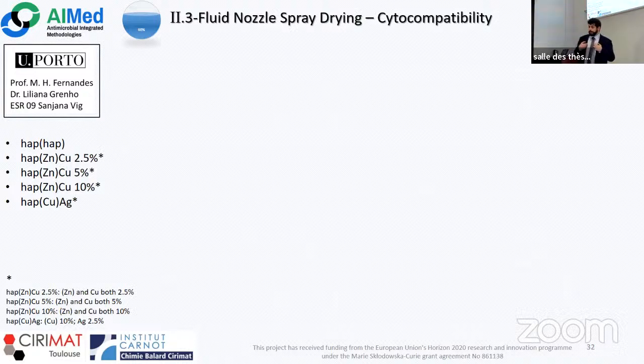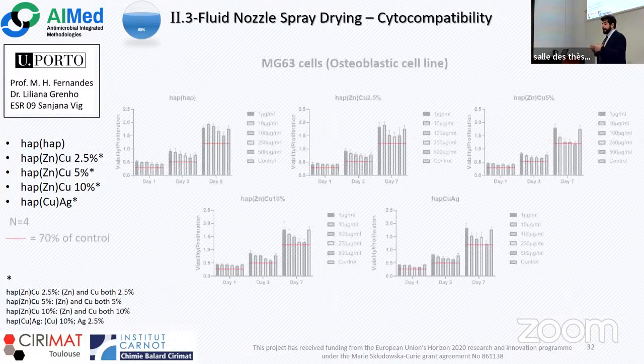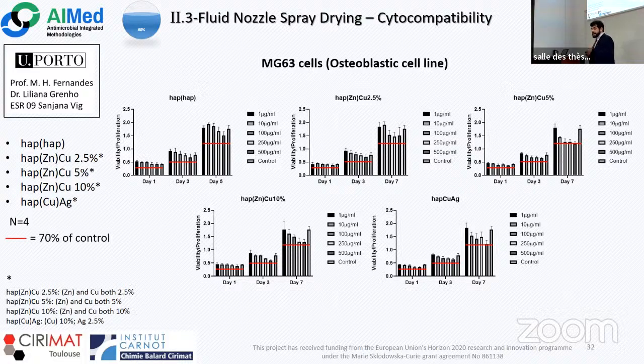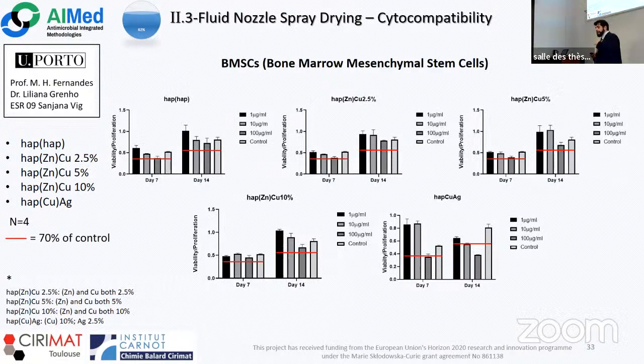And during my stay at the University of Porto, we studied the cytocompatibility against the MG63 osteoblastic cell. We can observe that generally, in all the conditions, concentrations and time points, we were above the limit of 70% of the control that assesses the cytocompatibility of a material. And we did the same analysis toward the bone marrow mesenchymal stem cells, and you observed the same behavior with the exception of the higher concentration of the copper silver apatite.